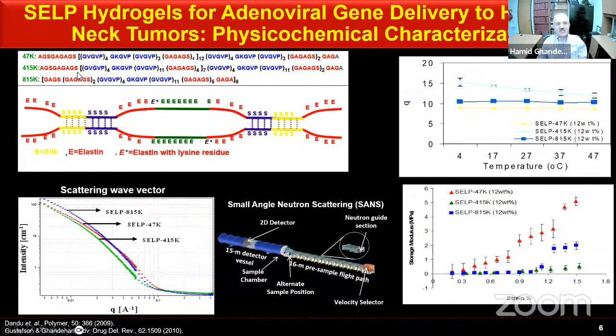We have systematically changed the length of these elastin and silks, and basically we came up with 3 structures, the first generation, which are 47K, 415 with a longer elastin unit, and 815 with both longer silk and longer elastin. And then we looked at the modulus of elasticity of these polymers. You can clearly see that silk 47K that has higher ratio, but also the specific sequence of silk and elastin has higher modulus. The 815 is somewhere in the middle, and the 415, which has long elastin units and shorter hydrogen bonded crosslinks, has lower modulus of elasticity.